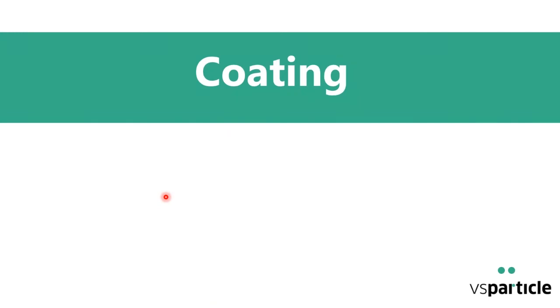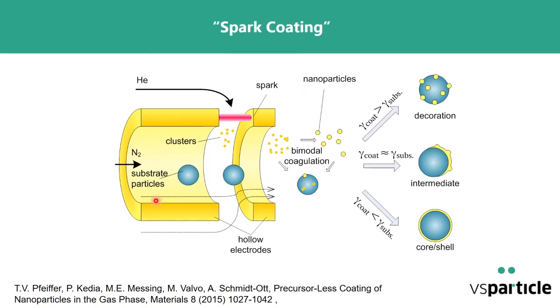A specific way of mixing is coating, and this is especially interesting also for catalysts. If you already come in with one particle, called the substrate particle, which can be produced by one spark generator, and you go through the hollow electrode of a second spark generator, you can then cover these particles with the vapor coming from the second spark. So this is the gap between the two electrodes where the spark is. And the spark moves around very quickly on this whole circle, so it's practically everywhere.